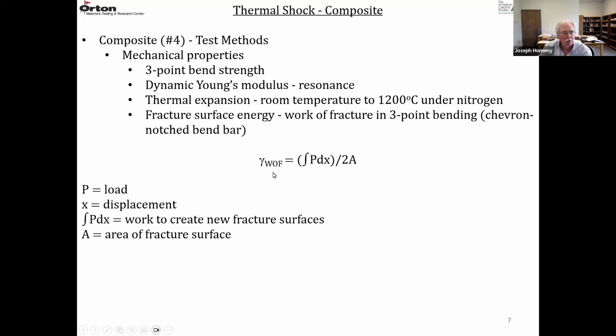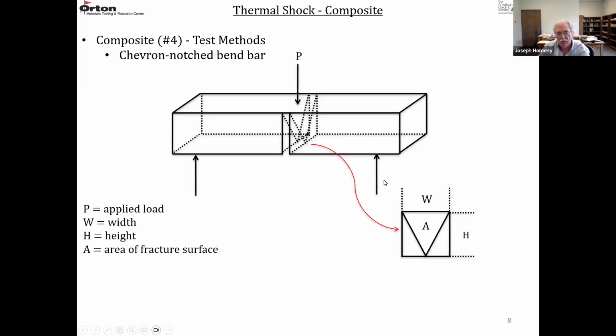bend bar. So we've seen this formula: the work of fracture equals the integral of P dx, the area under the load displacement curve, divided by 2A, and A is the area of the remaining triangle ligament. So this was the chevron notch. That's 3-point bending. The load is applied in the center, and then you have 2 lower knife edges. W is the width of the sample, H is the height, and A is this area that's fractured.